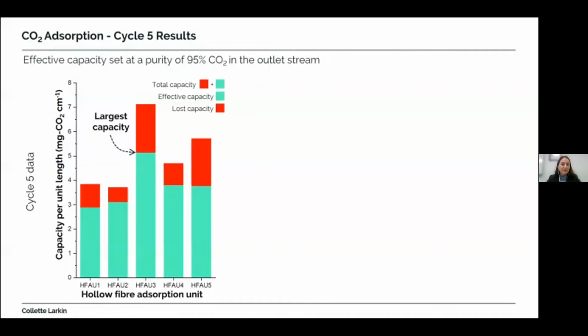And looking at the capacity per unit length obtained for each of the hollow fibre adsorption units at the 5th adsorption cycle, you can see that the hollow fibre adsorption unit that obtained the highest capacity per unit length was hollow fibre adsorption unit 3. And this behaviour can be explained by the thin coating of calcium oxide that was deposited inside the fingers of the hollow fibre adsorption unit, which maximised the surface area offered by the alumina hollow fibre support.